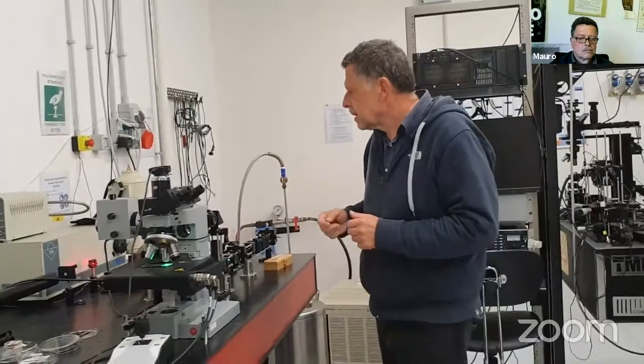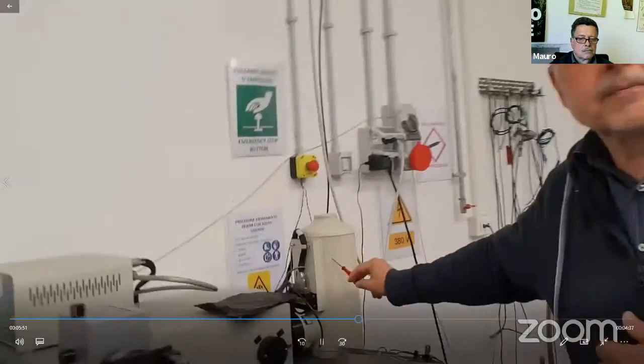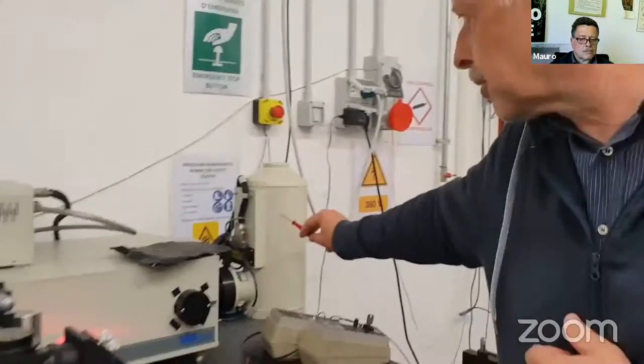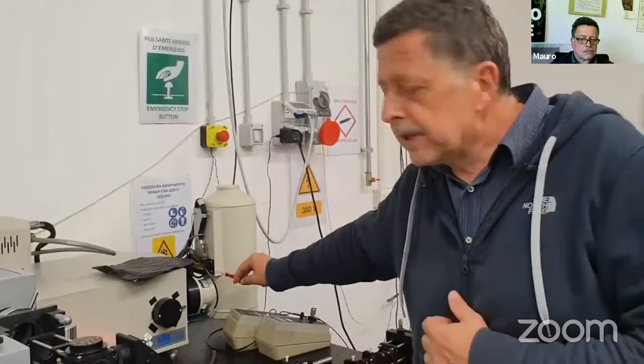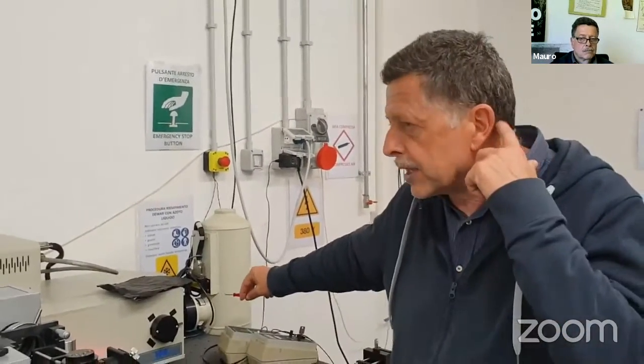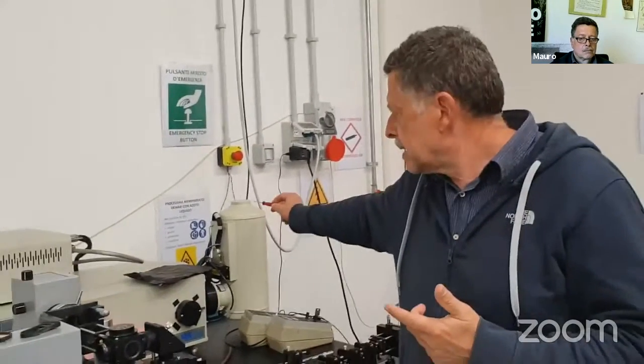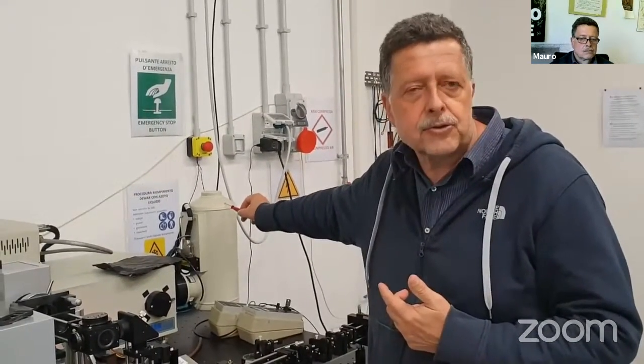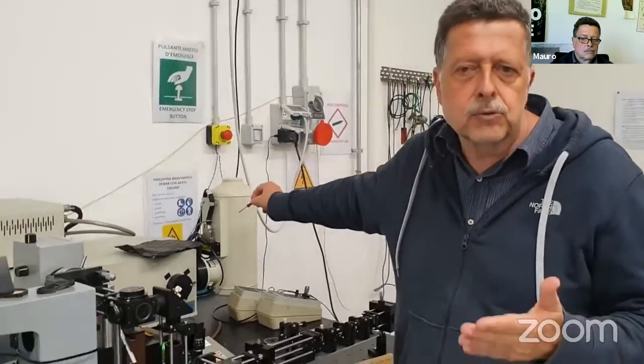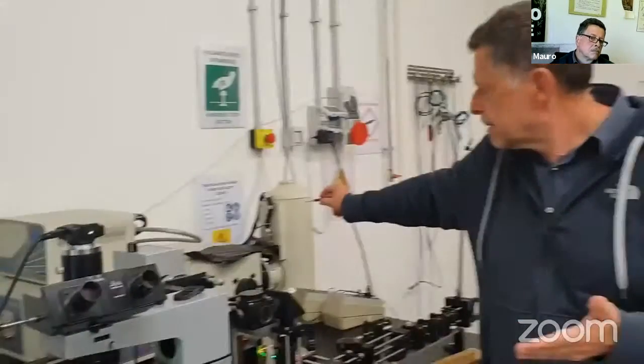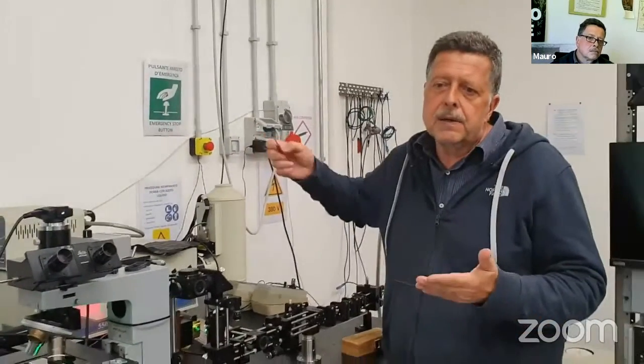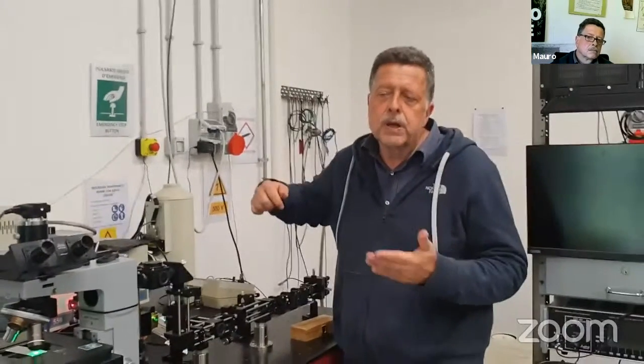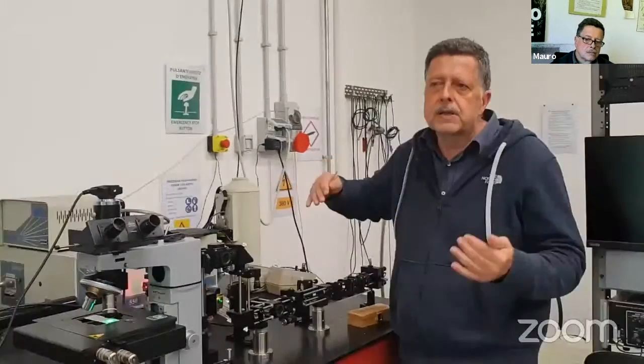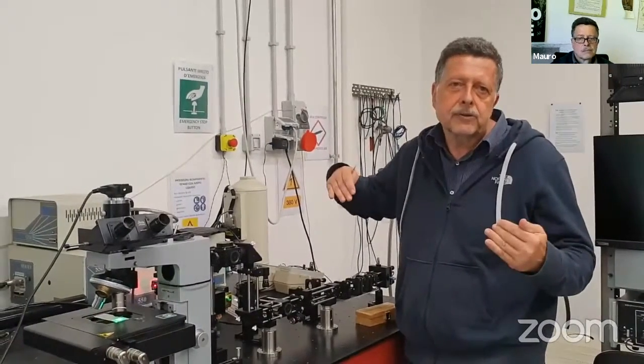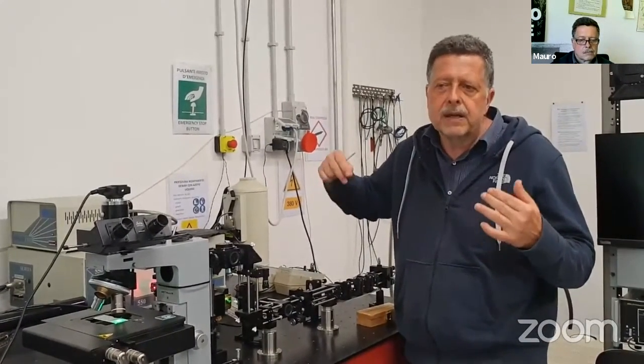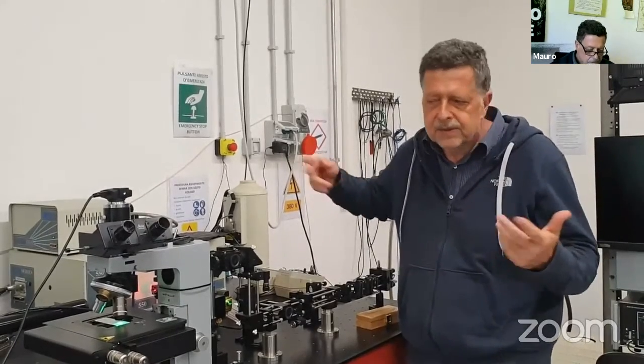The other feature is that we have a very low noise detector. This detector is a charge coupled device detector, which is cooled with liquid nitrogen. This is necessary for good quality Raman, because cooling down to liquid nitrogen temperature will decrease the noise of the detector. So you can see very, very small signals, such as the Raman signals.